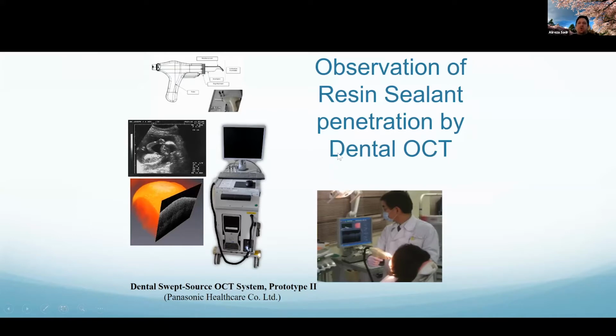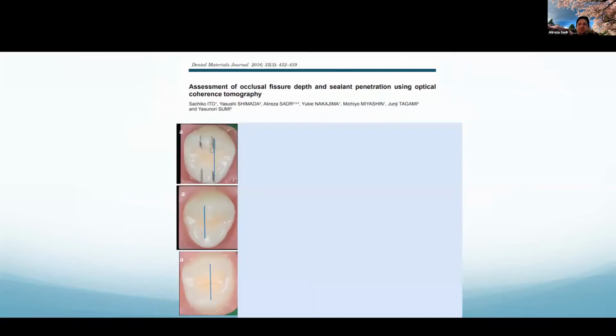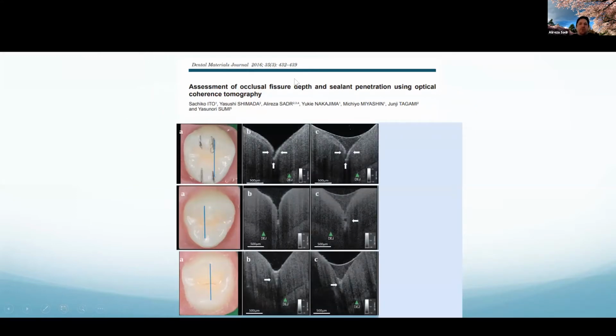So what we wanted to do was to look at the resin sealant penetration and see, even if you have a perfect isolation, can you really seal those fissures? So here's the publication. I think we came out in 2016. We did 3D images of the fissure, right? And then looked at the fissure basically after application of a resin-based sealant. You won't believe how many cases, and this is something you could do clinically. You could look at your fissure and then go ahead and apply the resin to find out that unfortunately, in a lot of cases, we do not have a complete penetration of the resin-based sealant into the fissure base, right?